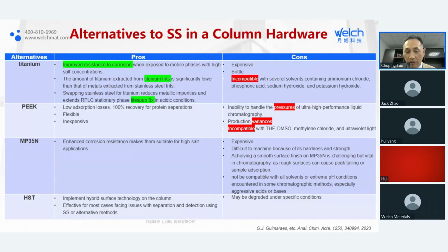Another observation is by using titanium, the lifetime of the C18 column increased 8 times. That's incredible. However, this metal is expensive, it is brittle. Also, it is incompatible with several conditions, say acids or base. So it has limits. So another material can be PEEK. Yes, it's a very wonderful material too. It's inexpensive, it's flexible, it has no adsorption loss. Sounds great. But the limitation is this kind of material cannot handle high pressure. So you cannot use this for UPLC at all.